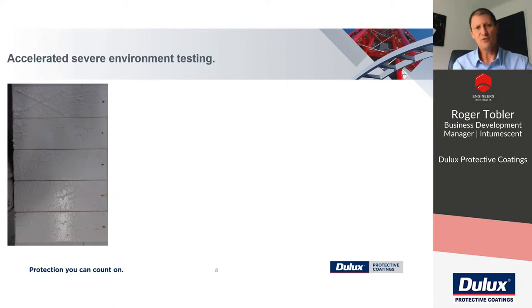So moving on to the next form of testing that's done on intumescent coating systems, complete systems, primer, intumescent, and the top coat. On the left here, we see the 3 coatings applied, and then they're exposed to a severe environmental testing regime of high humidity with salt and varying temperatures. And the system on the left is a water-based system. So it's an epoxy primer, water-based intumescent, and a polyurethane top coat.